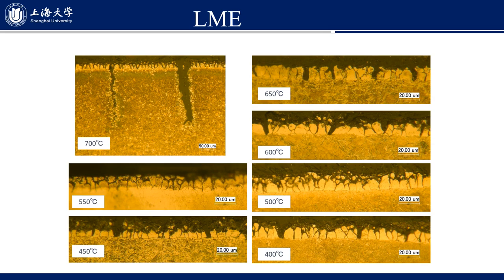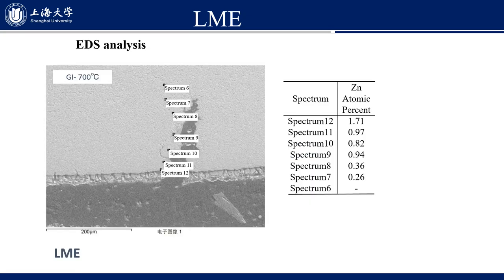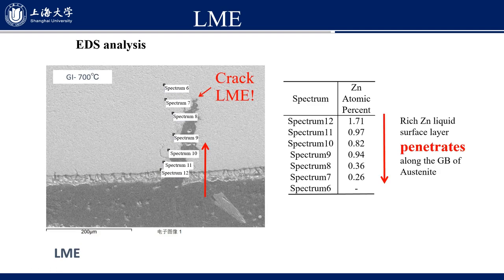This slide shows the microstructure of the steel after deformation. This is the microstructure of the specimen after the test, with cracks or free of cracks conditions. The EDS analysis shows that the zinc content of the specimen decreases and the zinc-rich liquid surface layer penetrates along the grain boundary of austenite.